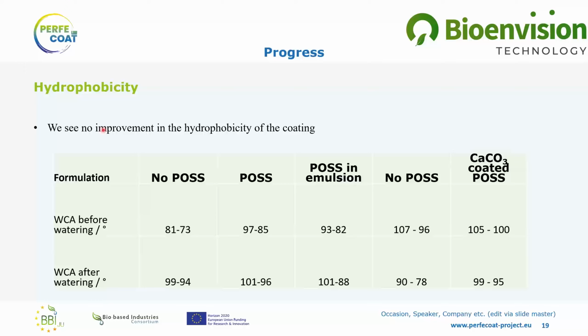Here tests were done to test the hydrophobicity of the coating with and without POSS. The first row here shows the contact angles of water droplets, which are 10 microliters, before watering or immersing the coating in water, while the bottom one shows the contact angle after the immersion into water for 24 hours.